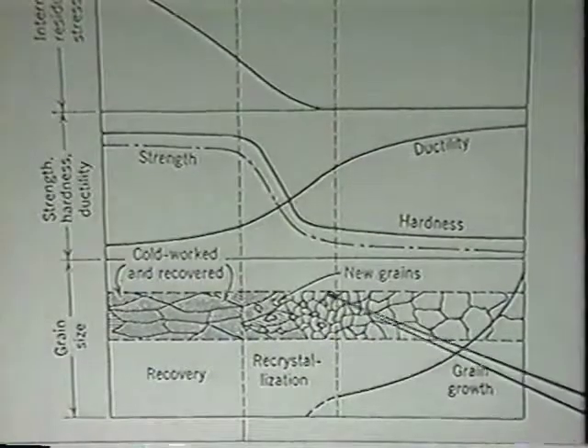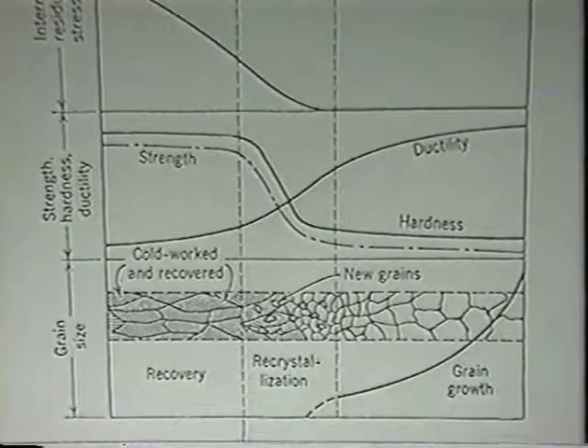Go ahead, Tim. DQSK is out at the upper end of the ductility. Where is the CQ then? The CQ would be right in here where we just get it to recrystallize so that we remove the full hard strength. But that's it. It's a cost-efficient process to get something you can form. There's a lot of variability in it, but it gets rid of all the cold work that's built in through the cold reduction process.